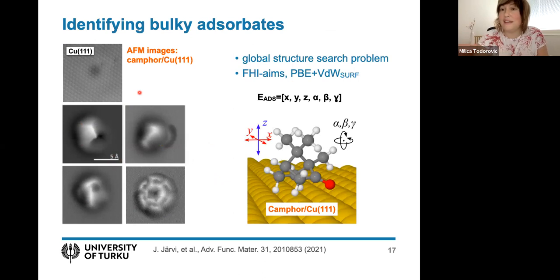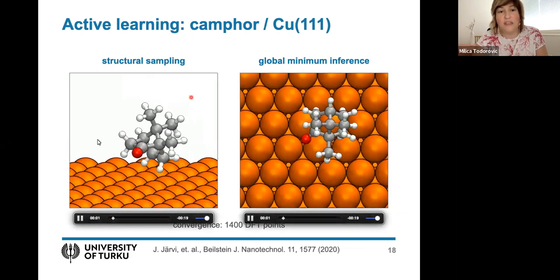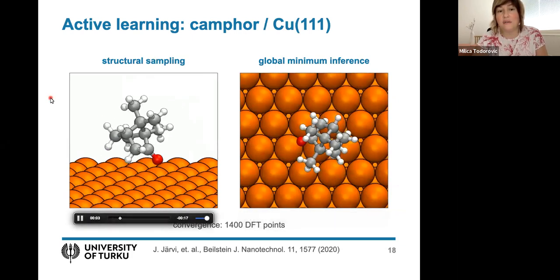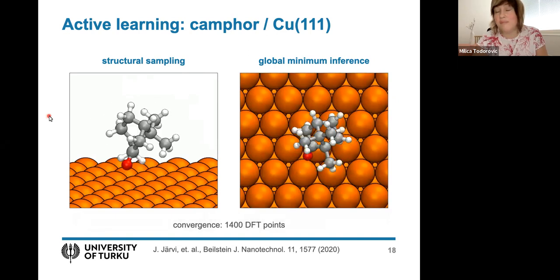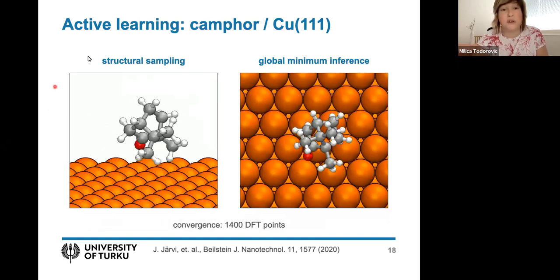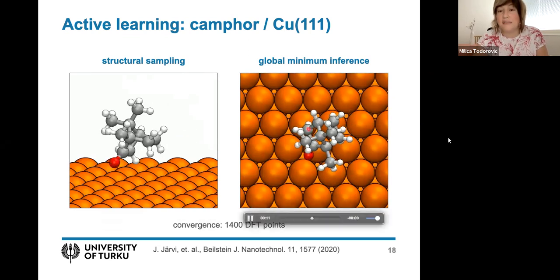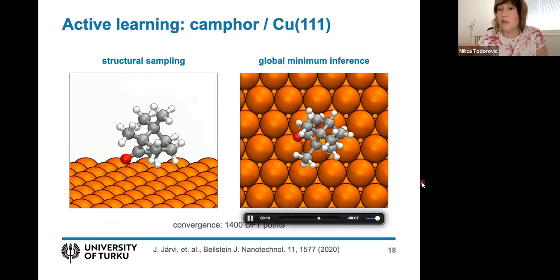So we did exactly what you saw in the previous slide. We put this camphor molecule on the copper 111 surface, and we were looking for adsorption energy minima as we changed the position and the orientation towards the surface. And this was, of course, all done with ab initio density functional theory and dispersion corrections. So here you can see, again, the same movie. Here on the left, you can see how BOSS runs structural sampling in an automated way on high-performance supercomputing platforms. And at the same time, we are learning about what the global minimum structure is.